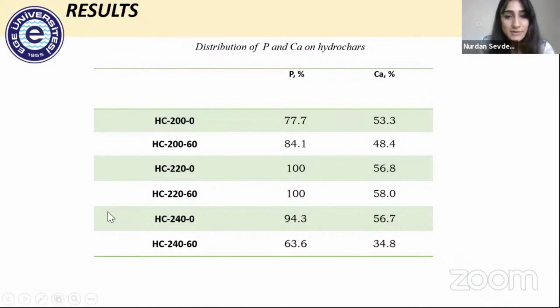As seen from the table, between 60 and 100% of phosphor remains on the hydrochar. On the other hand, most of the calcium in poultry litter, about 50%, also remains on the hydrochar.